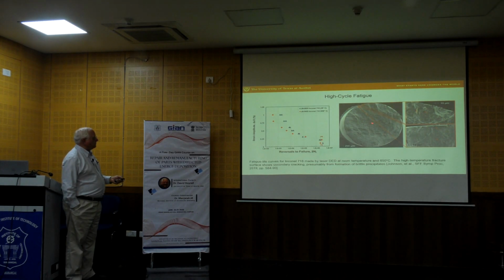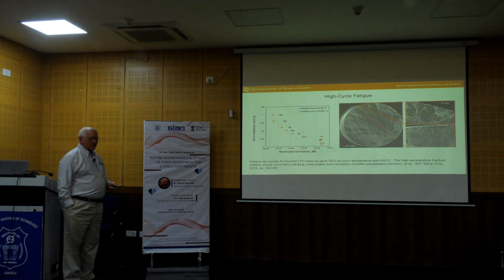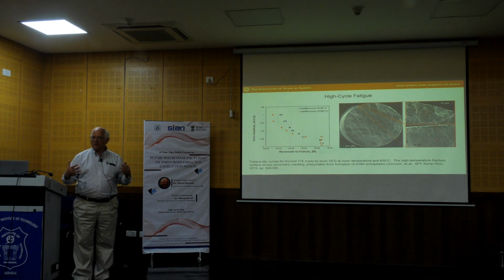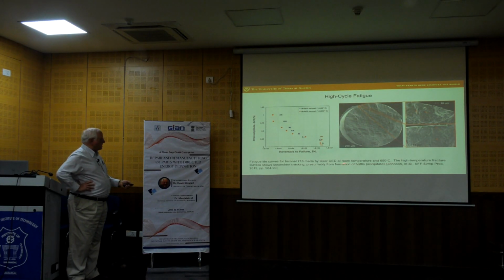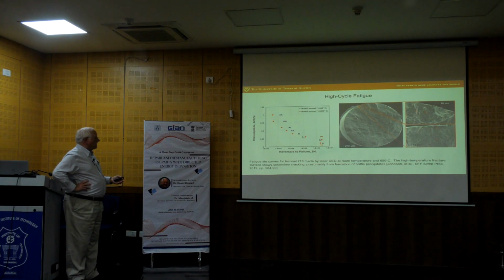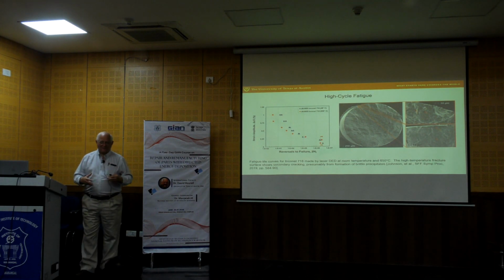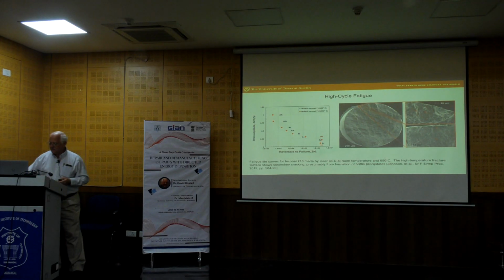This shows, not very convincingly, I think, a plot where we zoomed in on the surface where the fatigue cracks were initiated. And what they show here, again, it's difficult to see on the slide, is secondary cracks that have opened up in the process. They speculate that these come from precipitates at high temperature. But again, with fatigue properties, the defect structure really has a big effect.